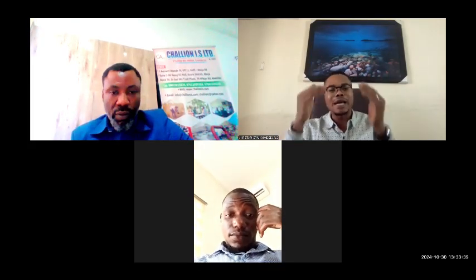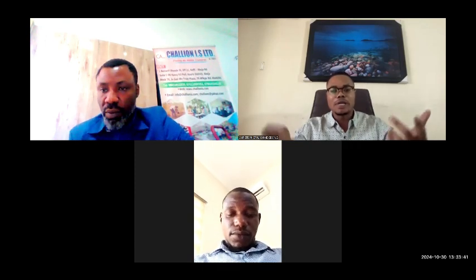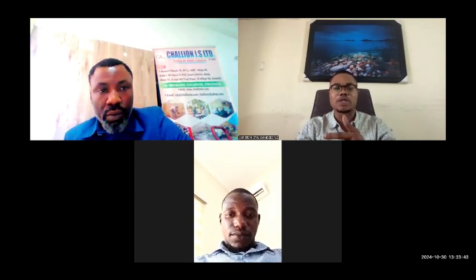So you can use that to calculate the grade of monazite. Then there's another unit, we call it TREO, total rare earth oxide. For TREO content, we are talking about the total content of the rare earth in oxide form. You can use your XRF to do that. Take, for instance, monazite: you have elements like praseodymium, Pr, lanthanum, La, and so on, and cerium as the highest constituent. You can use your XRF to get the elemental values, and then you convert each element to oxide, and then you sum up the total rare earth oxide to know your TREO. But there's another one again, they call it REO.